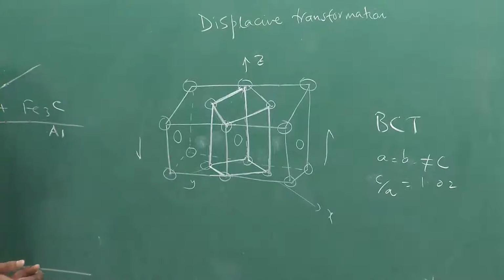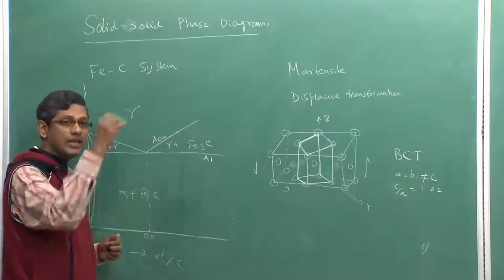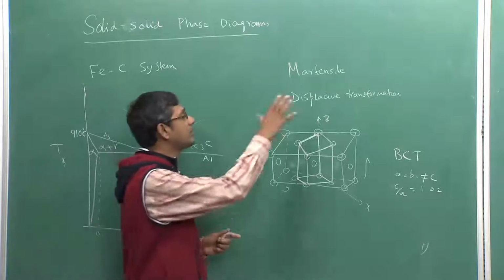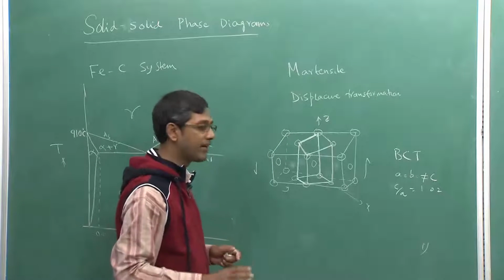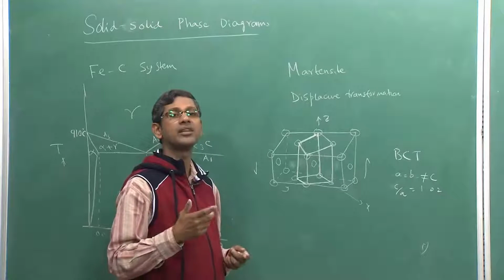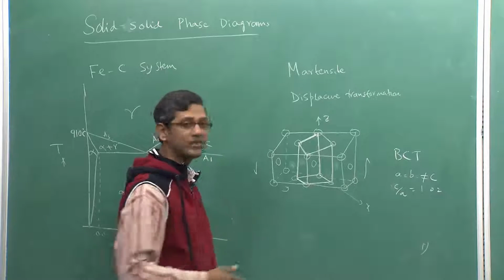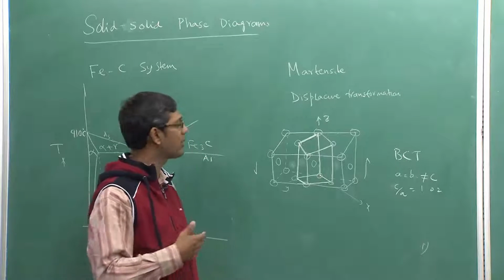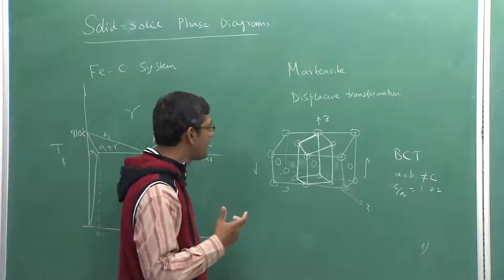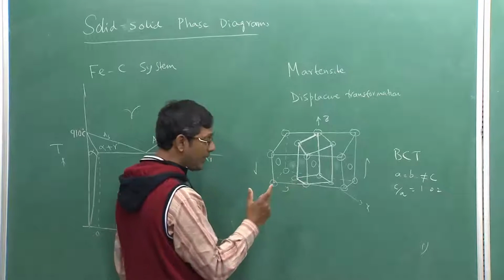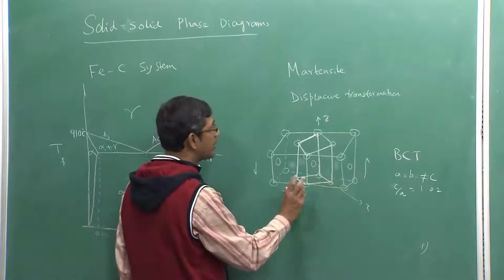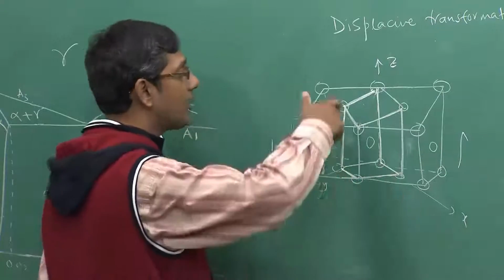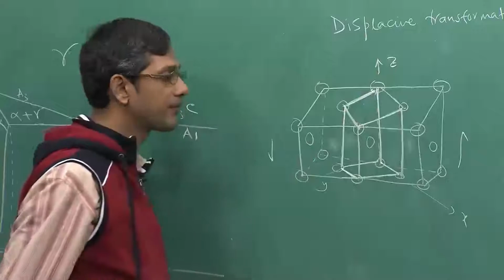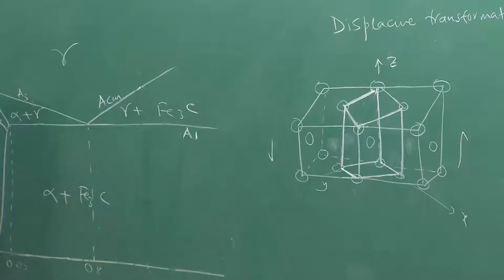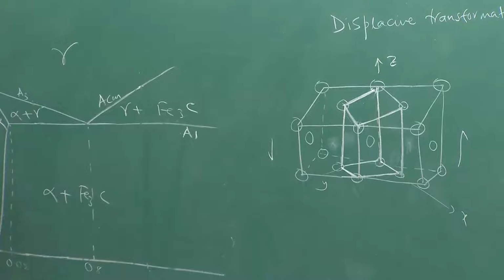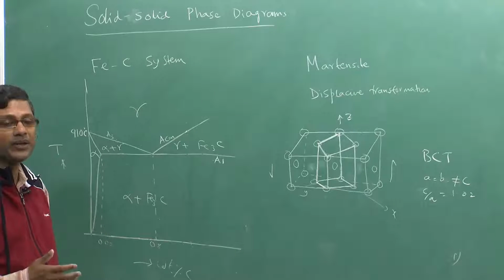You take the sample at 950 Celsius temperature, quench in water, and immediately the steel gamma will transform to Martensite. That means the rate of transformation is just like the speed of sound inside the steel, which is very high. Why does this happen at the speed of sound? Because what you basically need is to flip the unit cells from this position to this position. That is easy to understand, everybody can understand this. That is what actually leads to formation of different domains.